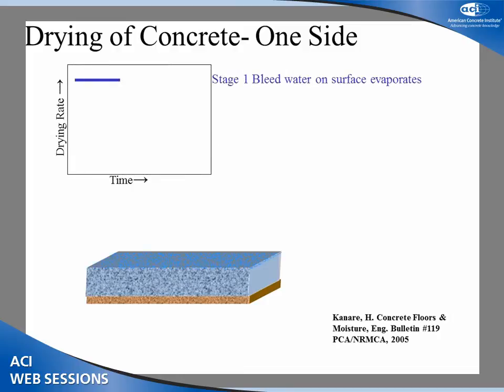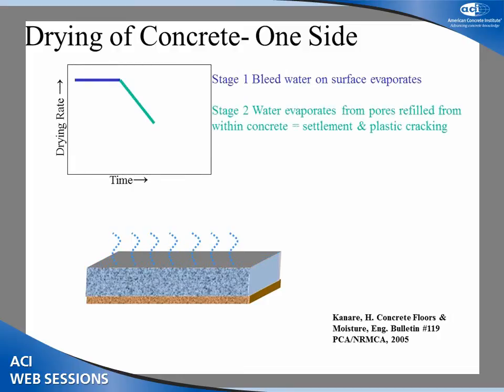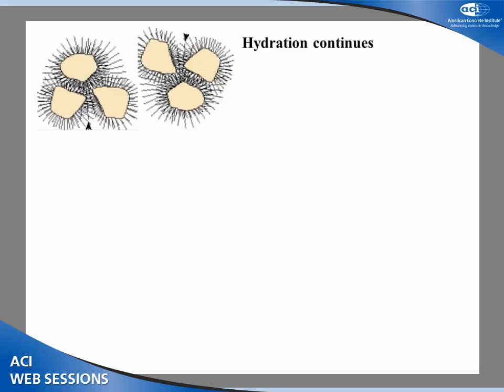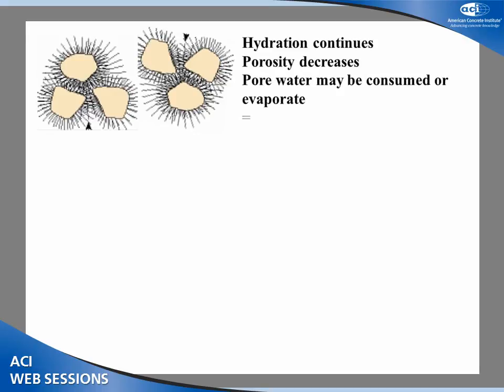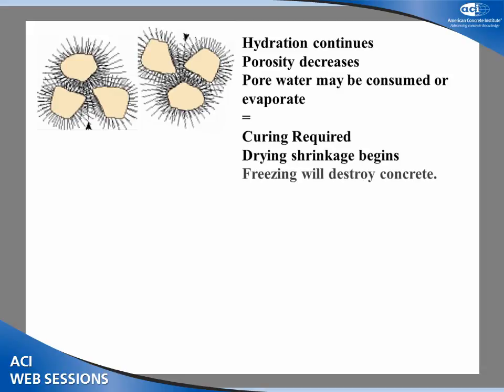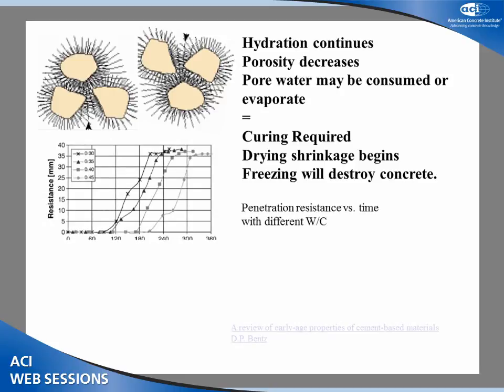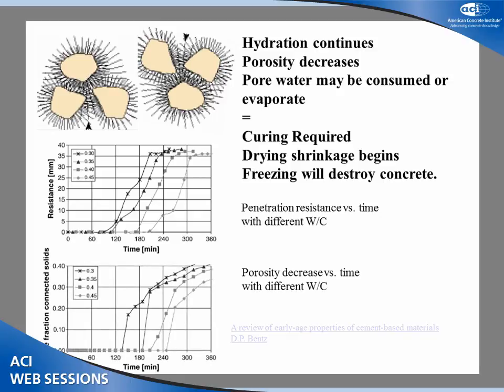How does concrete dry? Well, first I got the bleed water on the surface. It evaporates. Then the water evaporates from the pores and is refilled from within the concrete. And then finally water evaporates and I get drying shrinkage. Hydration continues, porosity decreases, pore water may be consumed or evaporate, curing is required. Drying shrinkage begins, freezing will destroy the concrete unless it's strong enough. Penetration resistance versus time. Here's strength, there's time, different cement mixtures, different water-cement ratios. And porosity. It decreases with time.